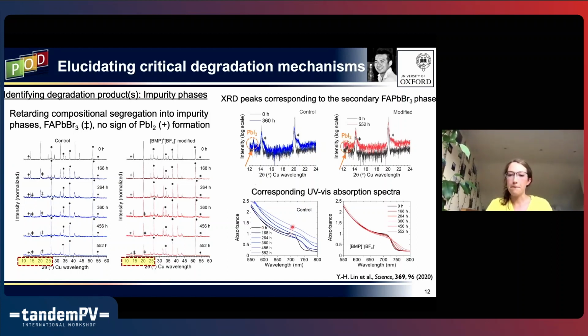We also see that corroborated with the UV-vis absorption spectra, where in the control sample, we lose that nice sharp absorption onset fairly early on in the aging process, and we see this red shift of the material. And you might be thinking, why is it shifting red if we're forming this FAPbBr3? That should be a higher band gap. You're right. But if this is phase segregating out of the bulk of the material, we're taking a wider band gap material out, so we see this shift. Also, we just lose the onset of the absorption spectra compared to the piperidinium, where we have good stability, and it takes a lot longer before we start to see any red shifting, just based on the absorption.